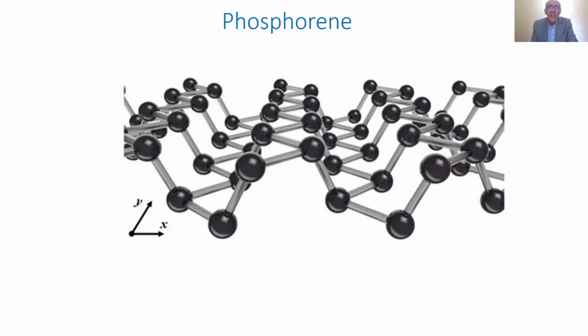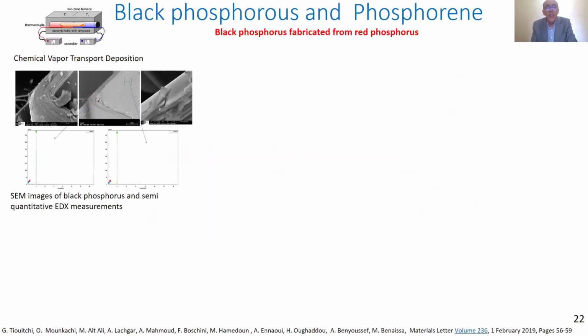This material has been obtained in the same way as graphene by exfoliation, but to make exfoliation, we need to look for a layered bulk material. And the layered bulk material for phosphorene is black phosphorus. As is shown here, this is a layer of black phosphorus. And this material is obtained from the red phosphorus, which is less stable than the black one, using a chemical vapor transport deposition.